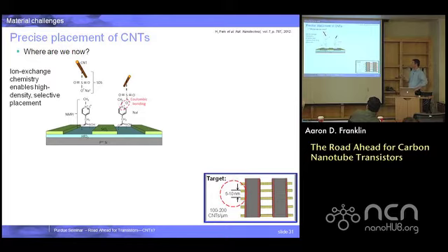This is the one that we've done a lot of development on at IBM. Really over the years, there's been good work there on it. And that is using some type of functionalization, either of the nanotubes or of the substrate or of both, in order to attract them selectively to different surfaces. In this case, using an NMPI molecule that selectively attaches to a high-k dielectric like hafnium oxide and will not attach to SiO2. And then having the nanotubes wrapped with one of the more common surfactants, SDS, which provides sort of a positive charge end where the NMPI has a negative charge end. So you have a coulombic bonding that takes place, putting the nanotubes on those surfaces.